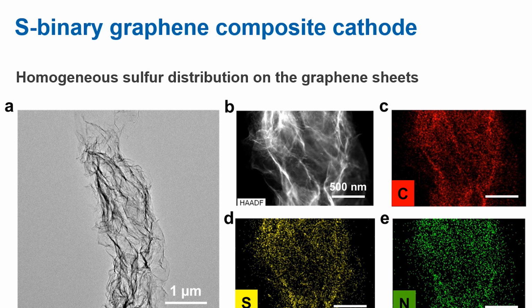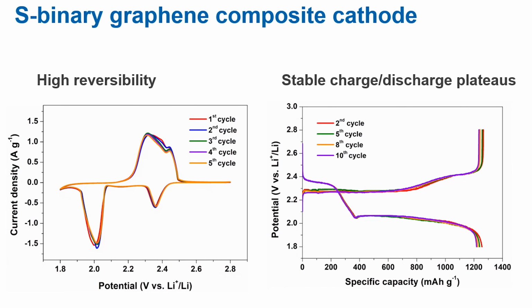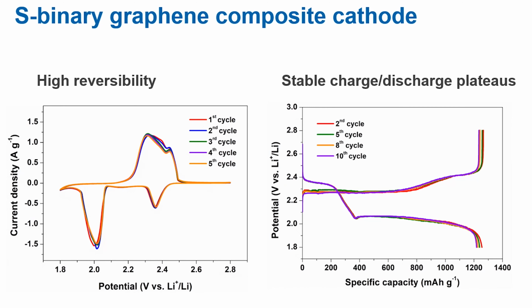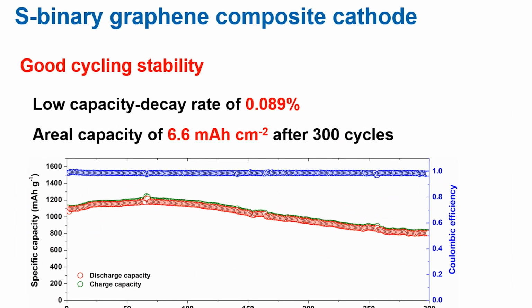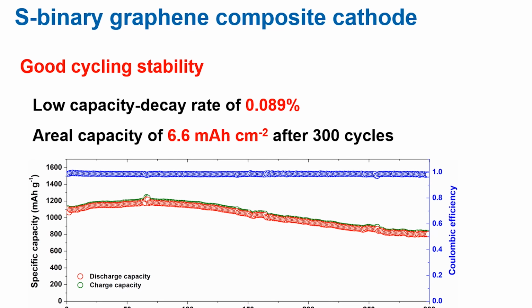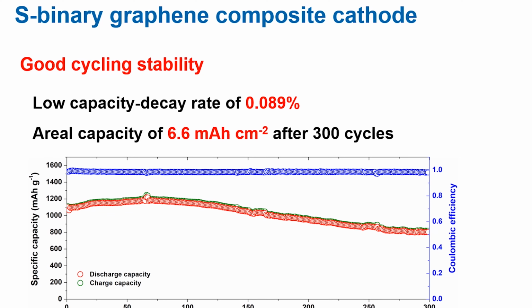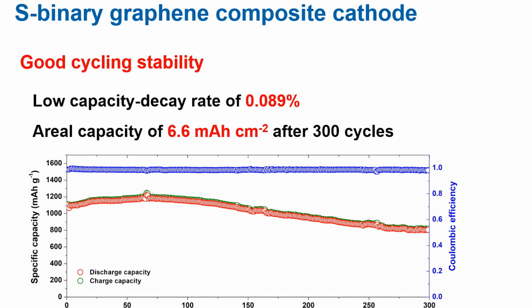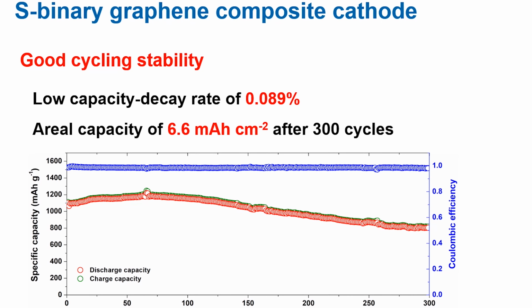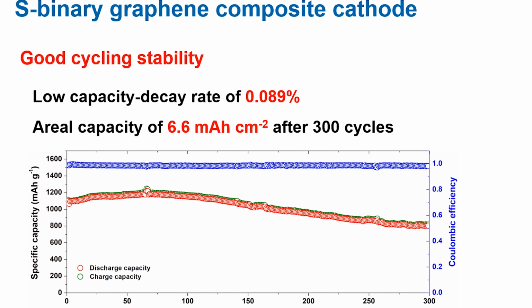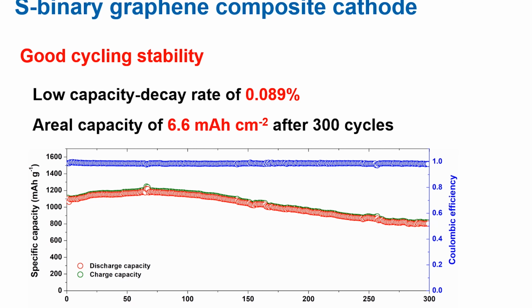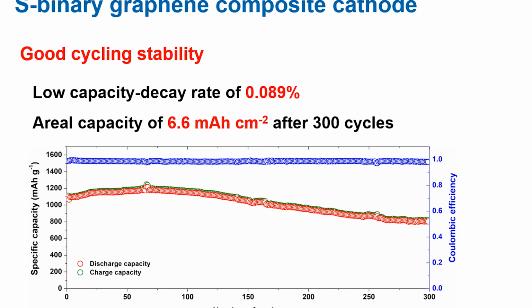From the STEM image and the corresponding elemental mapping, we can observe homogeneous sulfur distribution on the graphene sheets. From the CV profiles, we can see that the sulfur binary graphene composite cathode shows very high reversibility. And from the charge-discharge curves, we can see that the cathode shows very stable charge and discharge plateaus. The composite cathode also shows very good cycling stability with a very low capacity decay rate, and particularly it can maintain a high areal capacity of 6.6 mAh per square centimeter after 300 cycles. Those promising electrochemical results can be attributed to the microscopic and macroscopic design of the composite cathode.